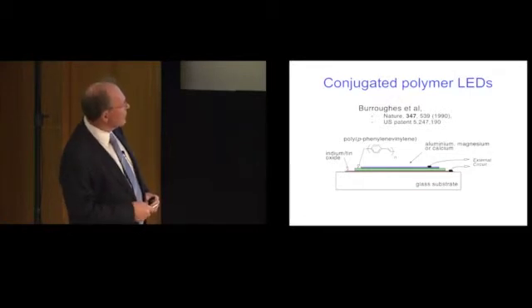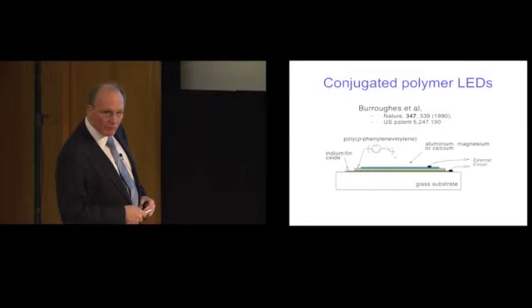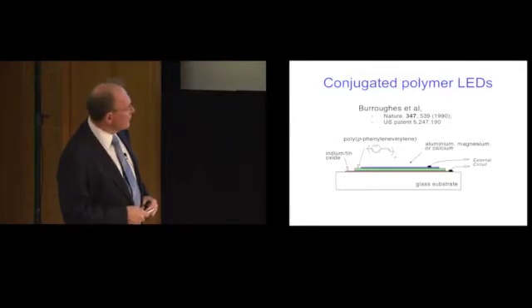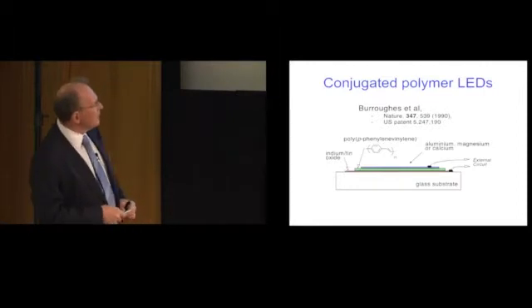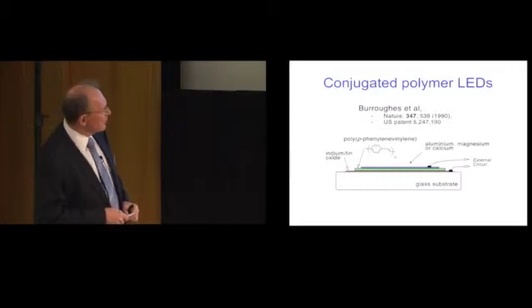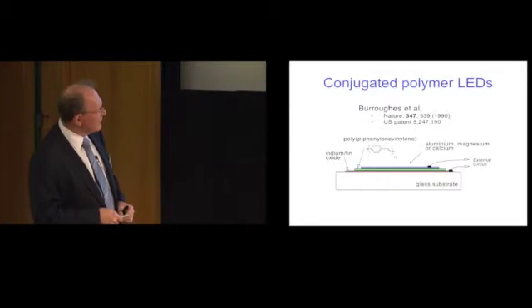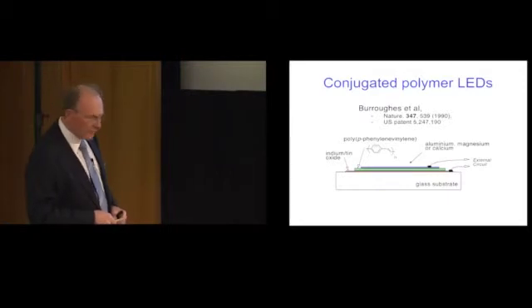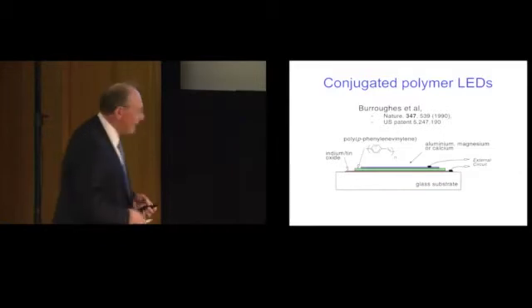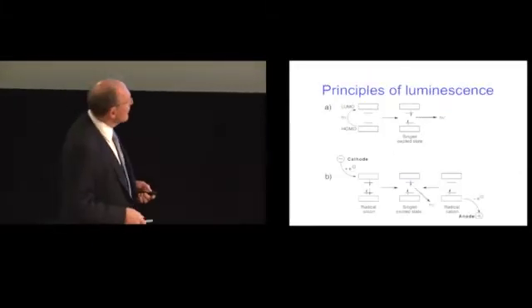So we have a thin film of this polymer deposited on glass on which there is a transparent electrode, indium tin oxide. So indium tin oxide on glass, the thin film of the fluorescent polymer, and then on top is a good negative electrode like aluminium or silver or magnesium or calcium. So this is connected to a battery, and the blue here is the silver electrode or magnesium. That is connected to the negative terminal of the battery, and the indium tin oxide is connected to the positive terminal of the battery, and the polymer gives out light, green light, because it's a green fluorescent polymer. So this is how it works.